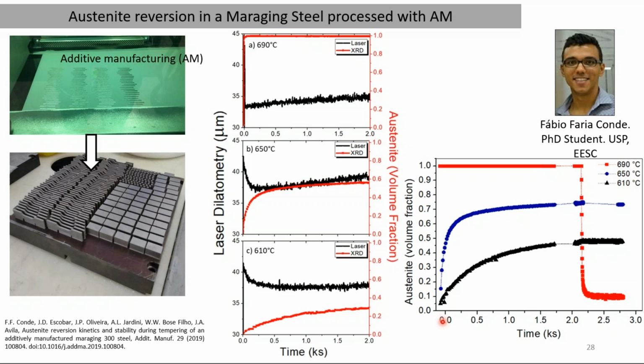On purpose, we used a really high heating rate in order to avoid any transformation during that step. And then we transformed all the material into austenite in a few seconds, a few milliseconds, and the material stays austenite until we finish this isothermal step. We see that, let's say, 100% of the material is austenite. When you cool down to room temperature, you get less than 10% of austenite.